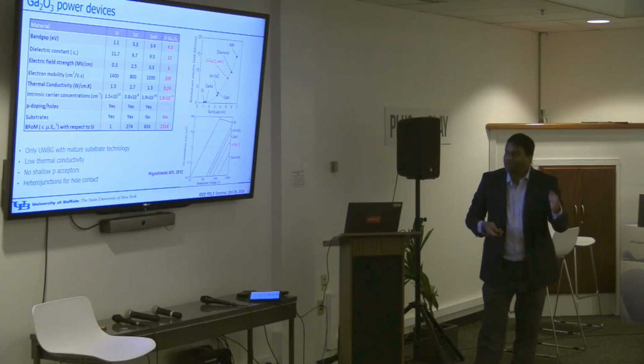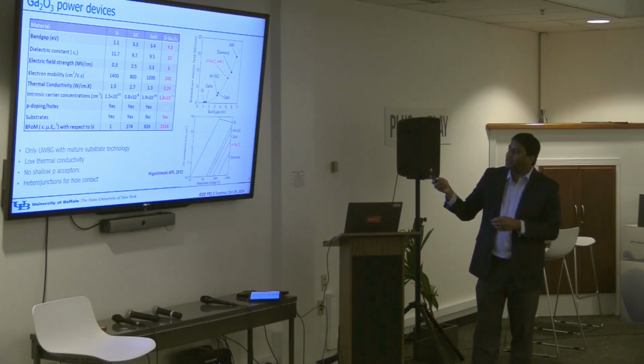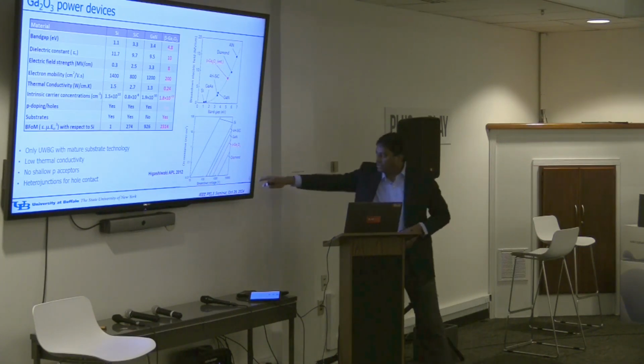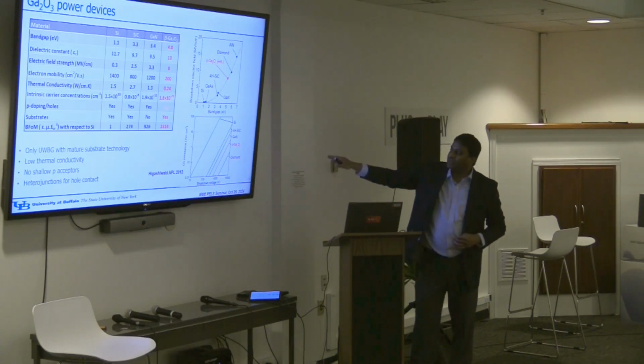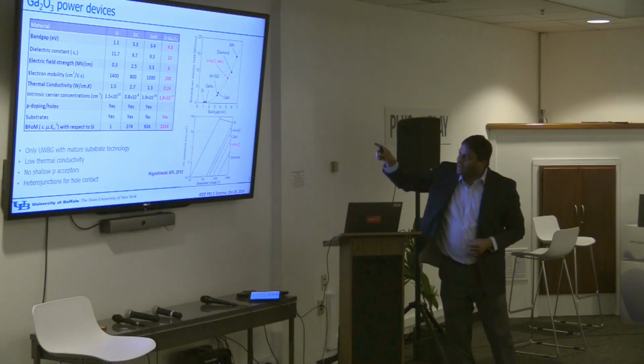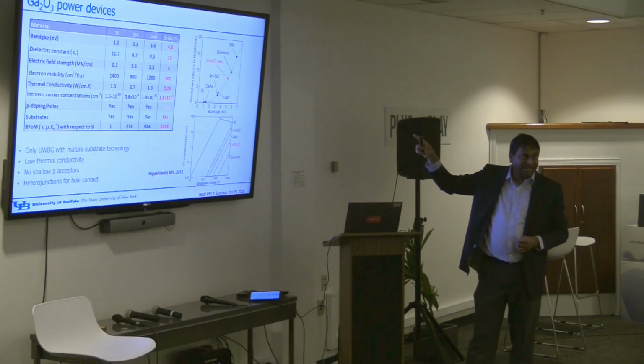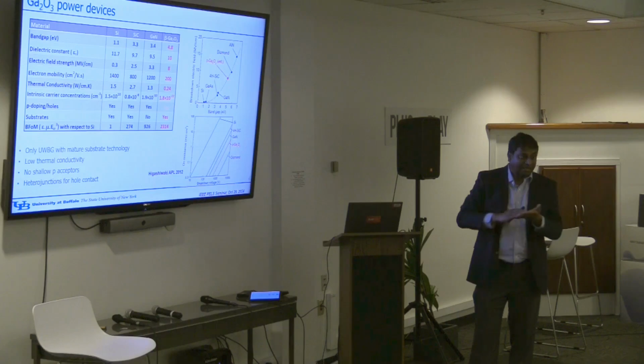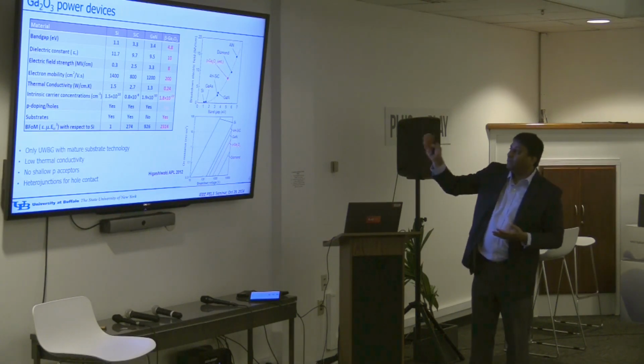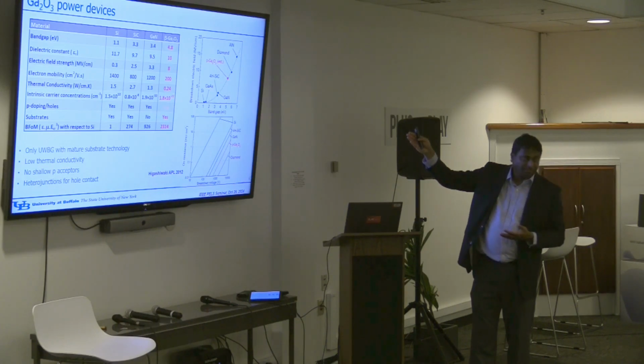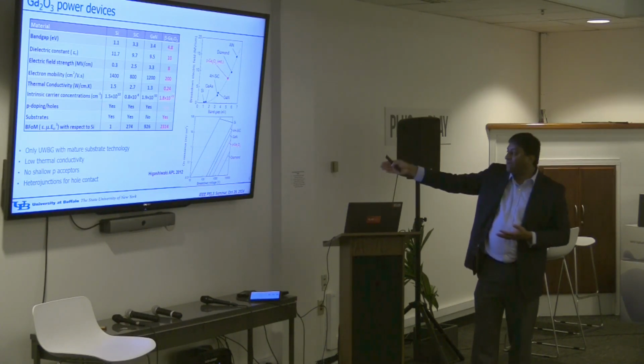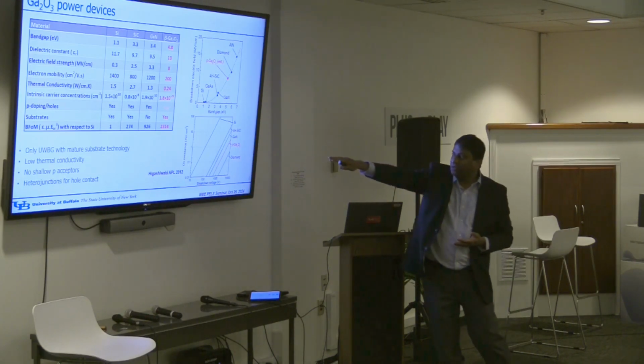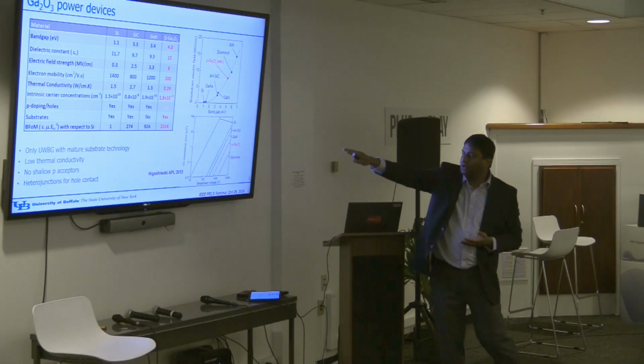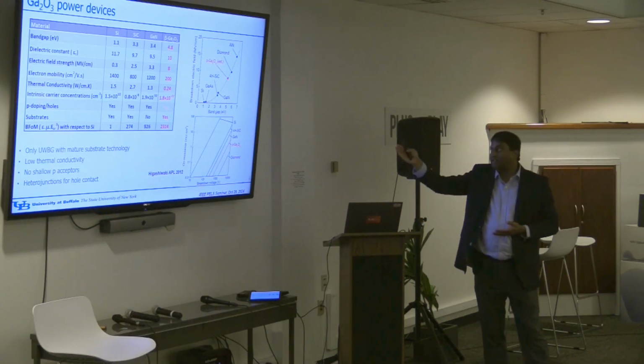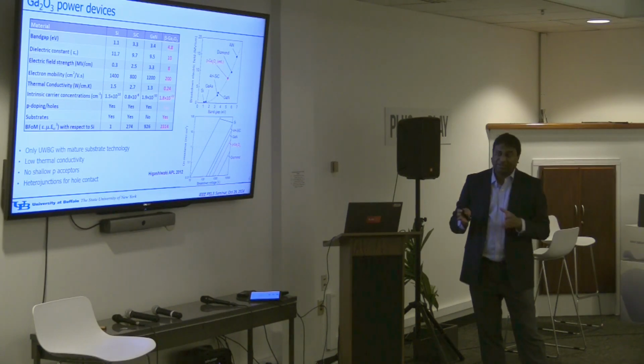Now, if you use the same argument for an ultra wide bandgap semiconductor, you can see that we can have low on-resistances and high voltages for this gallium oxide semiconductor. And if you look at the mobility value, it's 200 cm²/V·s, and that's actually pretty decent mobility. In fact, it's better than the silicon carbide channel mobility that you have in the products now. But if you compare with gallium nitride, the mobility is not that high. But for very high voltage applications, as we know from Baliga's figure of merit, it goes as the critical field cubed, and that's where you see the advantage over, say, silicon carbide or gallium nitride. Now, of course, this material has some challenges.